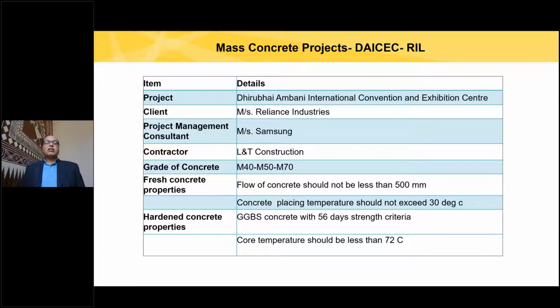Please note, this is a self-compacting concrete. The slump is not measured vertically. It is not the vertical slump cone measurement, but the horizontal spread of concrete. It is something like, you know, when you pour dosa batter, how it spreads. Concrete also should spread like that, and there should be no segregation and no bleeding. Therefore, you must make a cohesive concrete. Second thing is, this is also temperature controlled. The placing temperature should not exceed 30 degrees centigrade.